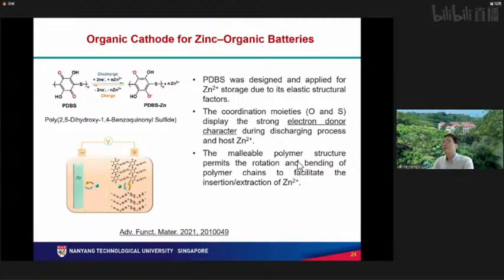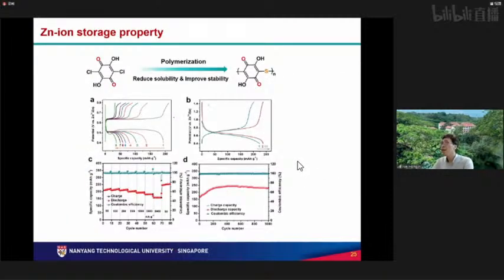But most organic materials have a relatively low voltage, no more than 1.5 volts, sometimes even just 1.0 volt. Okay. So in this work, we developed and fabricated PDBS polymers. Okay, it's kind of a polymer chain to host zinc ions. Of course, before the polymer chains, there is the precursor material. We also checked the precursor material. Actually, it can also interact with the zinc, but the problem is that the hysteresis, the polarization, is huge. Okay, we don't want this. So if you make the polymer chain, we find that the polarization can be slightly lower. Although, let's not pay too much attention to the voltage profile. The voltage is quite low, right? It is not really a cathode material.